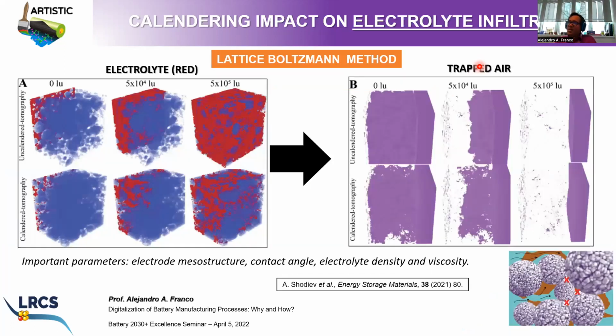But something that the model can provide as well is a prediction of where the air is going to remain trapped inside the electrode porosity. And this is very important because if you have air which remains trapped in some regions of the electrode volume, then some part of the active material is not going to be properly wet with the liquid electrolyte, right? And so you are not exploiting the maximal capacity of your electrode, because some parts of the active material have more trouble being intercalated with lithium ion, or deintercalated.